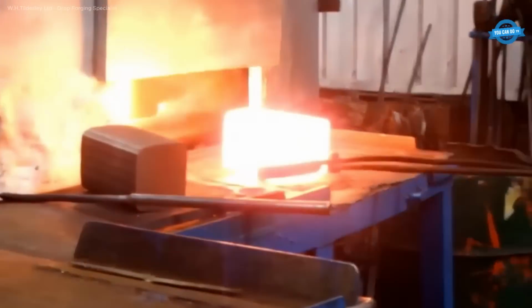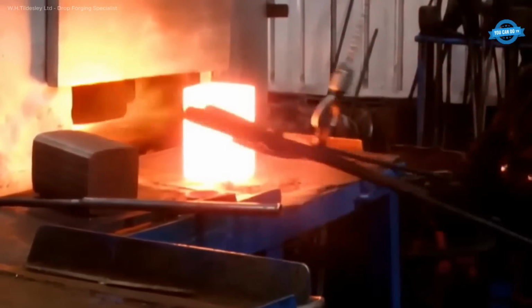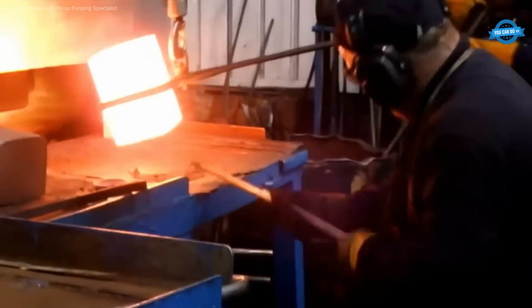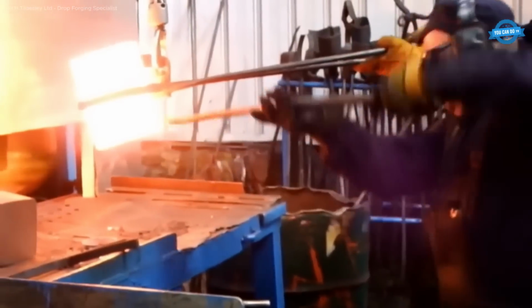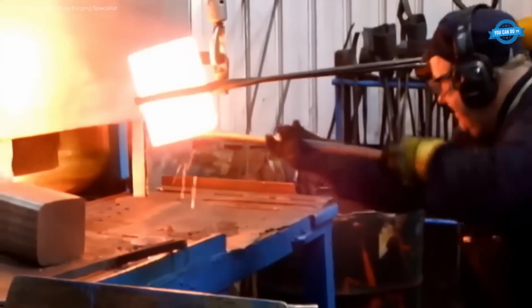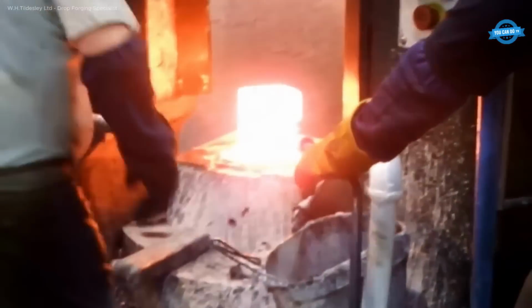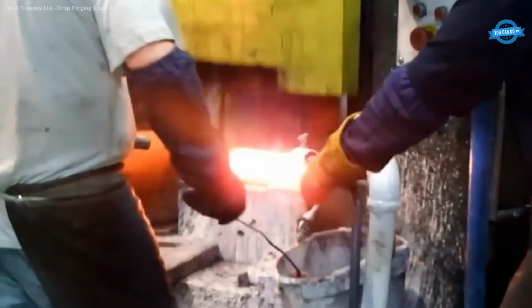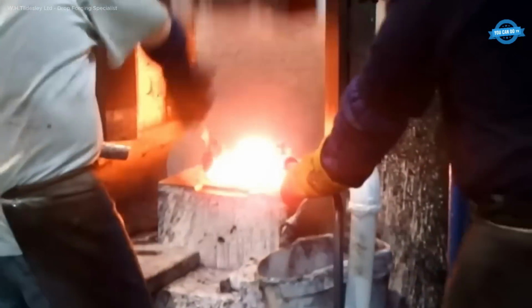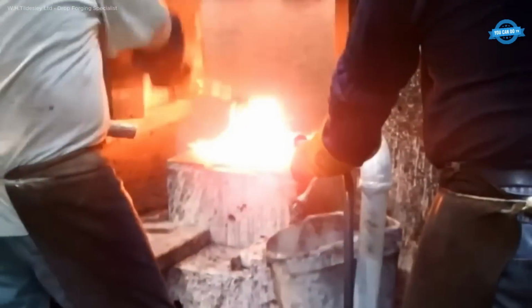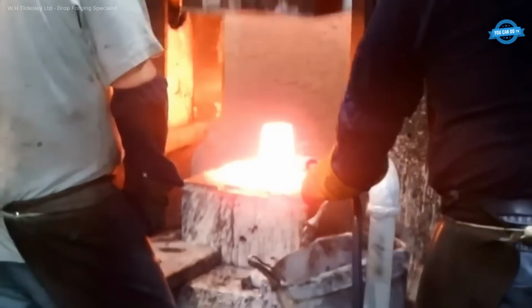This process showcases the precision forging of stainless steel flanges using closed die drop forging technology. Starting with certified super duplex stainless steel, NORSOK approved for demanding offshore applications. The billet is heated and shaped under extreme pressure using custom dies. The closed die forging method ensures repeatable dimensional accuracy and superior grain structure alignment, critical for mechanical integrity.